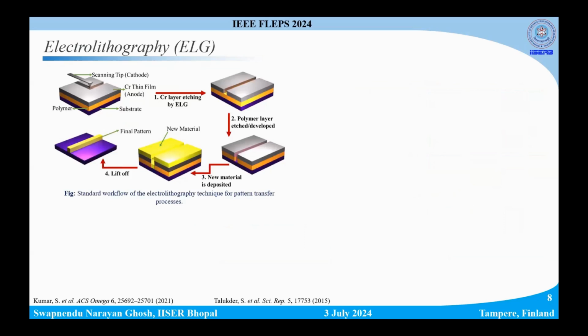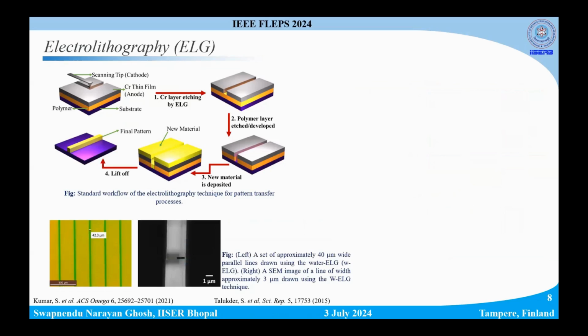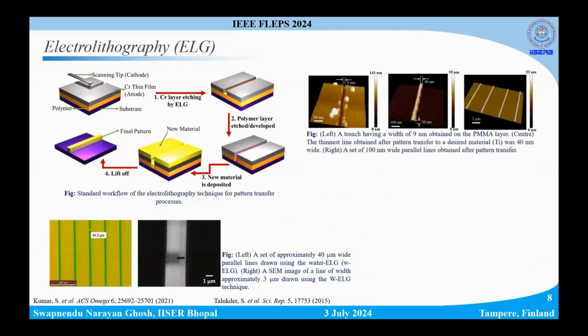So let's look into what electrolithography is. Basically, we electro-etch the chrome layer, and thereafter we can easily transfer the patterns that are formed on the chrome layer by using lift-off. In a hydrous environment, repeatable patterns of up to 40 microns have been achieved, with a best case of around 3 microns. All of these results are using micro-scale tungsten probes. When we tried to replicate the same thing using conductive AFM tips, we were able to obtain patterns of up to 9 nanometers, and successfully transfer the patterns to a different material of around 40 nanometers in width.